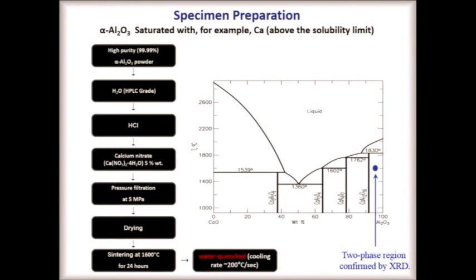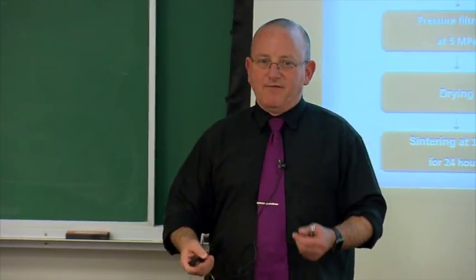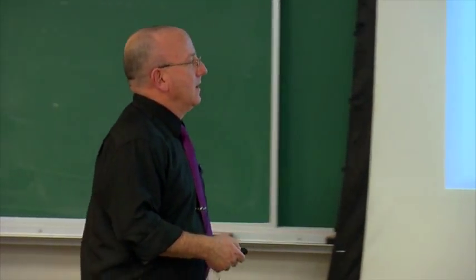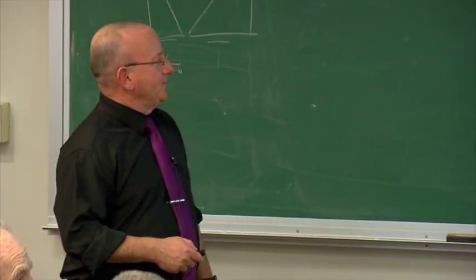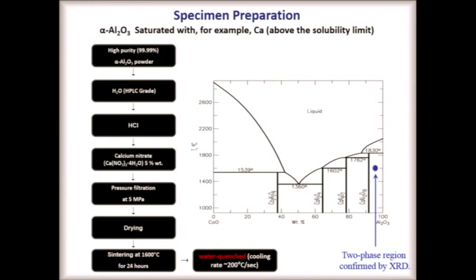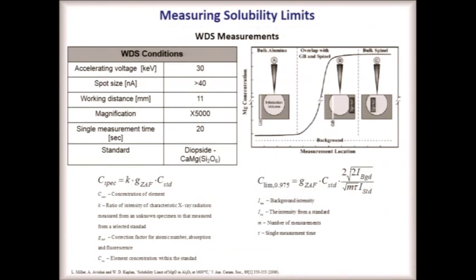Then we do something we don't allow the students to do, and we open the furnace at 1,600 degrees, take the sample out, and drop it into water. Actually, my students are always there. They have fire extinguishers aimed at me when I do this, and that's really not a bad idea. And then we do a WDS. The idea with WDS is because of the counting statistics, we can get to detection limits, which are obviously significantly better than EDS. They're not quite as good as SIMS, but of course the errors in SIMS are horrific, and standardization in SIMS is problematic. So here we have to do fully standardized analysis.